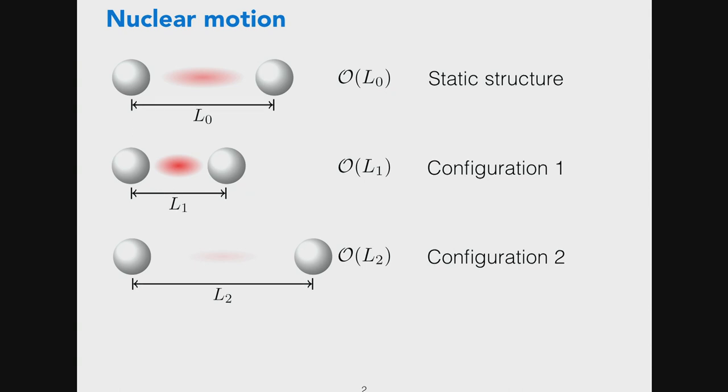A relevant property in this context might be the dipole matrix elements. Now, when we want to include the effects of ionic motion or temperature, we need to take into account the fact that the ions are no longer stationary at their equilibrium positions, but move about. For most of the talk, I will assume the adiabatic principle, which means that when the atoms explore other configurations, such as shorter or longer bond lengths for the molecule, the electrons instantaneously relax to the new configuration in which they sit.